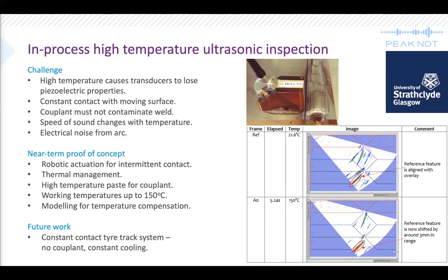You then have EM interference from the welding process and the arc itself, and the high power sources that you incur in thick section welding. You also have temperature issues: if you've got strong temperature gradients throughout your workpiece, the speed of sound in that material will change, which presents a challenge to sizing the defects accurately. And then additionally, you have a system that's designed to detect and quantify interfaces in material. Prior to welding, you have a full interface, and then as you're depositing each layer, that interface changes. So it's how you mask and prevent the system from detecting just the edge of the weld and the weld preparation as you're filling through it. So there are a lot of challenges that need to be overcome.